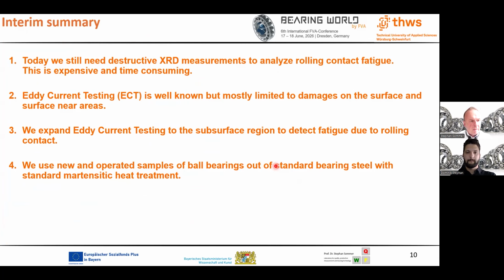So now let me quickly sum up and give you an interim summary. Today, we still need destructive X-ray diffraction testing to analyze rolling contact fatigue. This is expensive and time-consuming. Eddy current testing is well known, but mostly limited to damages on the surface and surface near areas. We expand the eddy current testing method to the subsurface region to detect fatigue due to rolling contact. So we use new and operated samples of ball bearings out of a standard bearing steel with standard martensitic heat treatment.